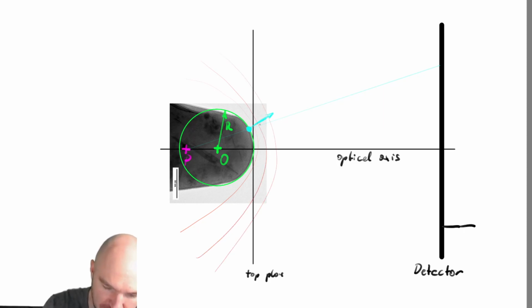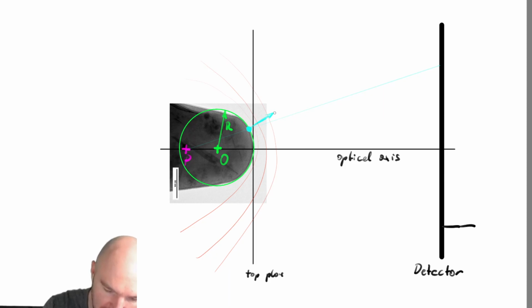Because you have a shank, essentially the electric field is going to push the originally radially leaving atom, not just in a purely radial path, but the path is also going to be a little bit inwards curved. It's going to come back to the optical axis a little bit. And the shank of the sample is going to repel your atom. If you've got a very wide shank, obviously that's going to be a stronger effect than if you've just got a very narrow shank.